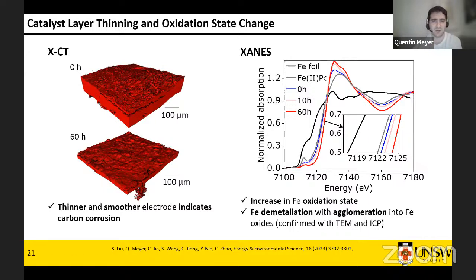So that's one step. The second part is we did some XANES measurement, X-ray absorption near edge spectroscopy, and we see basically a shift towards higher values. What this indicates is we have a higher oxidation state, an increase in iron oxidation state. And what we can propose is we have demetalation of iron, and then our iron turns into agglomerates of iron oxide nanoparticles. And we confirm that with TEM, we were able to observe them. And we confirm the demetalation with ICP because we detect a lower mass of iron after different stages of degradation. So that sort of confirms what I believe, but these are just physical measurements, not chemical measurements.